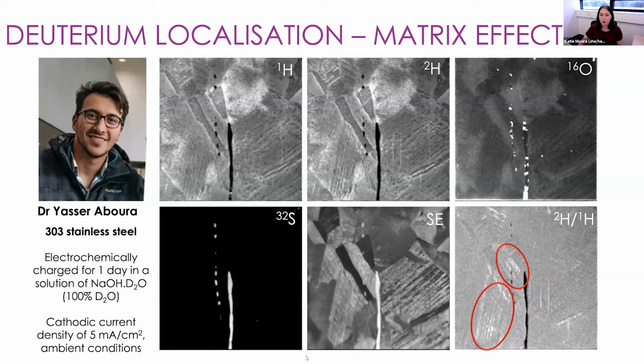For this particular steel example, you can see that the deuterium is localizing to dislocation slip bands. You can see we've got quite a deformed microstructure in this as received steel here. So we can see very clear enrichments of the deuterium. And interestingly, and we're still working on this, we don't really see any deuterium localized to the manganese sulfides. So this was really not what was expected according to the literature. So we need to think about that a little bit further.